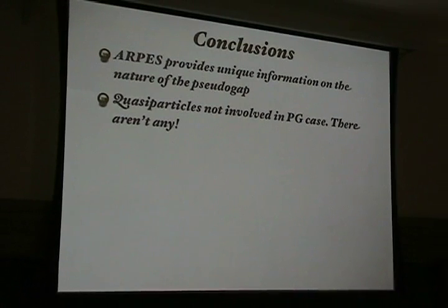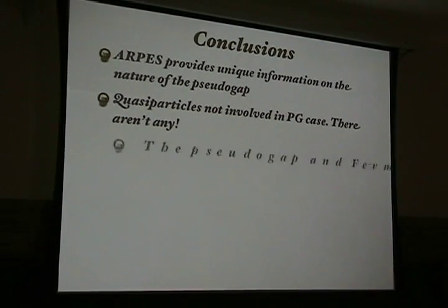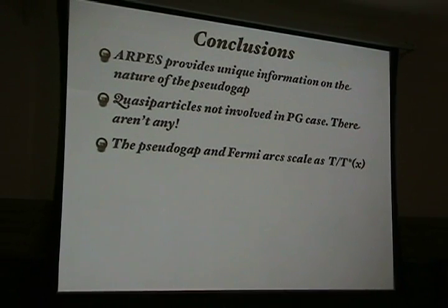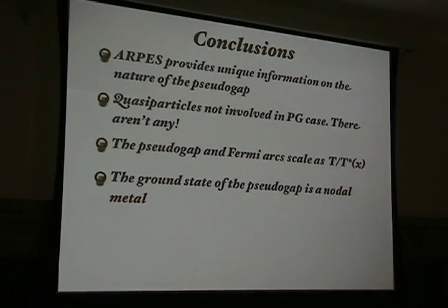And we do not have quasi particles in the pseudogap because there just aren't any. So you cannot explain anything in the pseudogap using a weak coupling theory that just uses quasi particles. You're starting from the wrong point. We also find that the pseudogap and Fermi arc scale like T over T star, and that the ground state of the pseudogap might be a nodal metal. We can't really prove that until we get there,